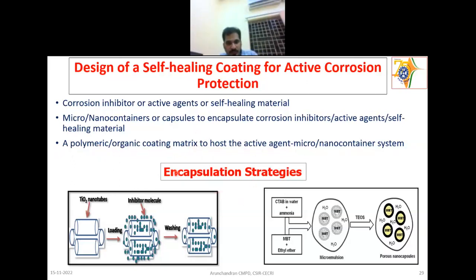So there are two types of encapsulation strategies. One such strategy which we made: you make TiO2 nanotubes, and then in the nanotube, the inhibitor molecule at a decided concentration, mix it under vacuum, and then you do the washing to remove anything on top. So make sure that your inhibitor is inside the container. This is known as post loading. That means you are making the nano container first and then loading the inhibitor.